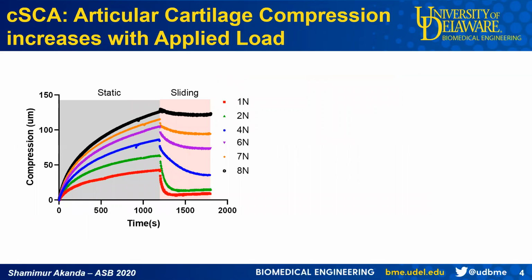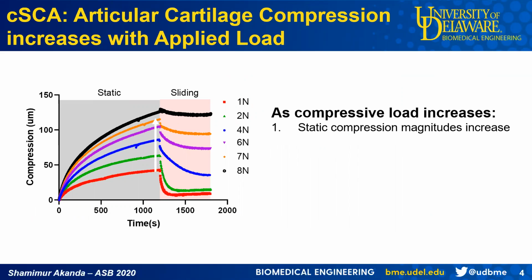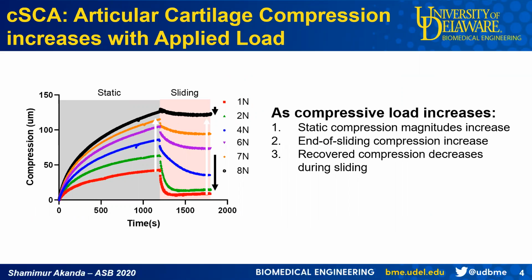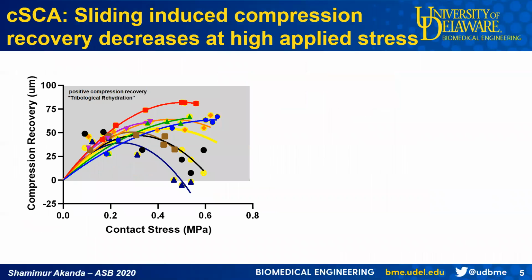Here I am showing the compression versus time graph of a representative explant for different loads. We see that as compressive load increases, static compression increases, end of sliding compression increases, and recovered compression decreases during sliding.